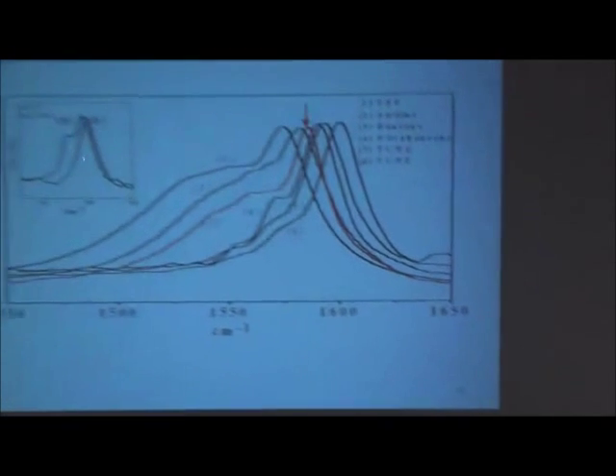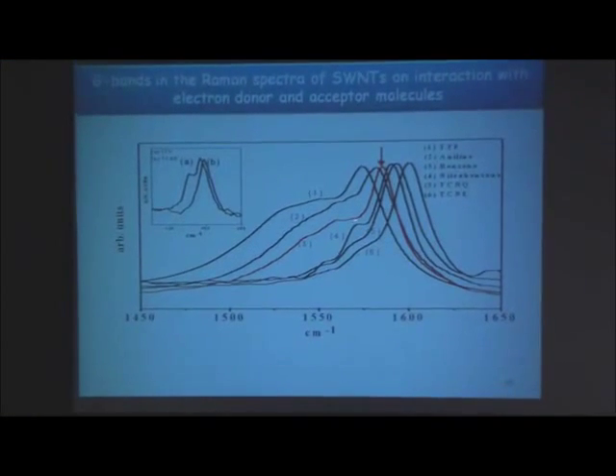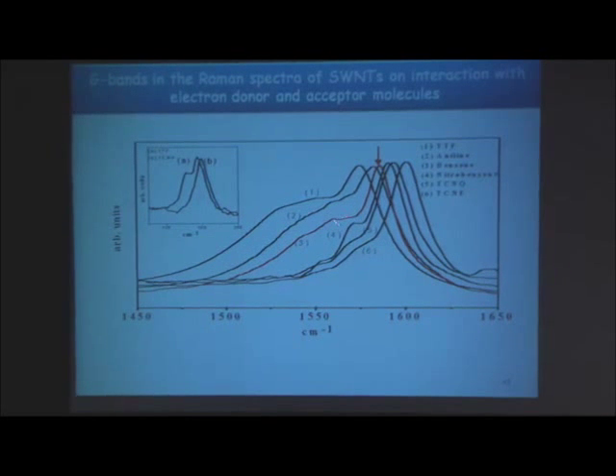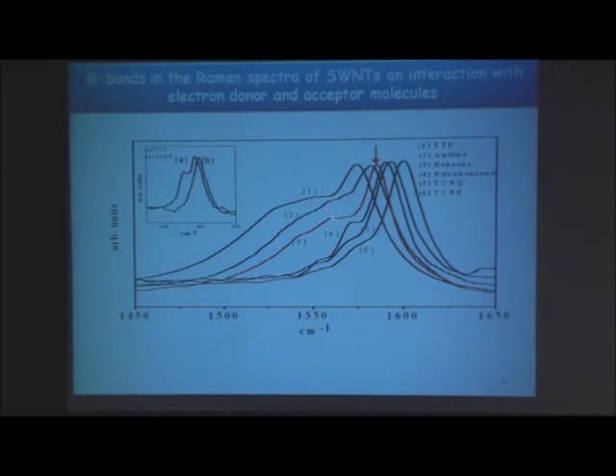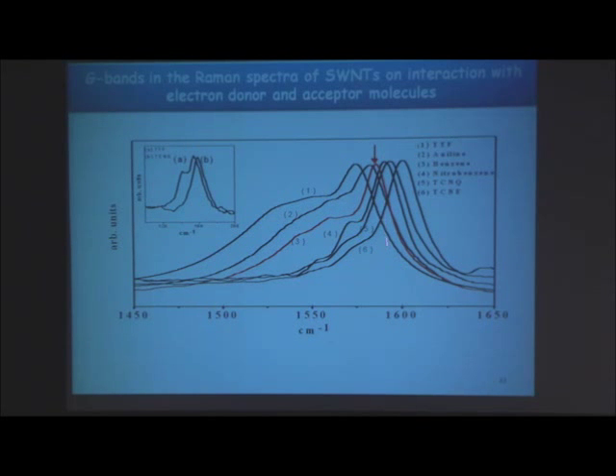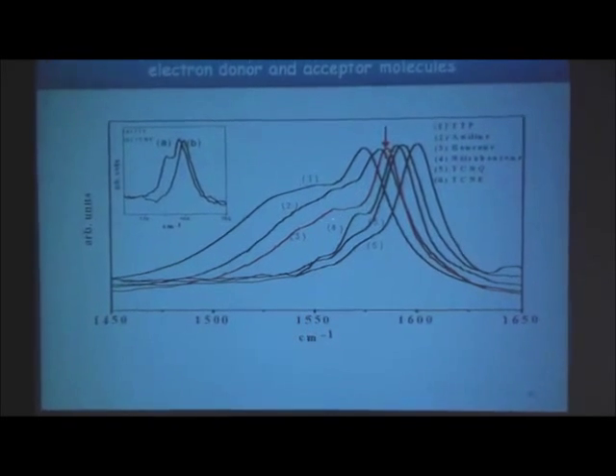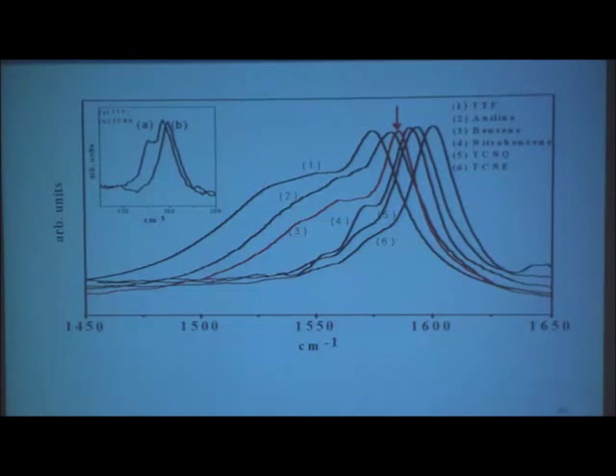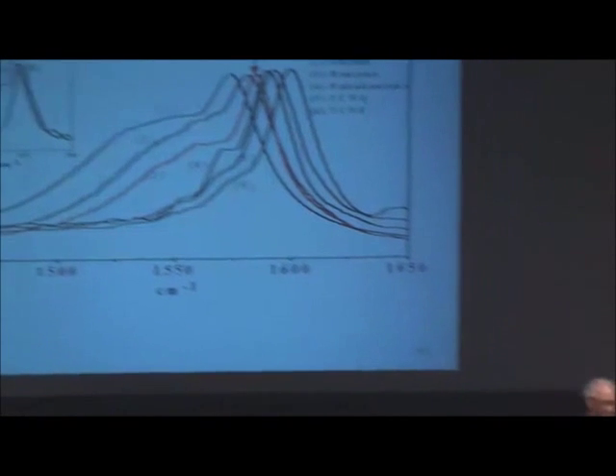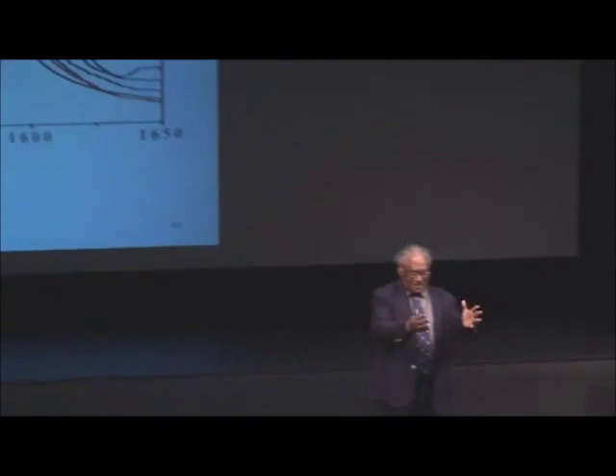This is the Raman spectrum. You see, the red spectrum is the spectrum of nanotubes as you make them. As you make it, it is a mixture of semiconducting and metallic nanotubes. That shoulder there, 1540, is characteristic of metallic nanotube. The big red band is mainly due to semiconductor nanotube. How do you know that? Well, there is a very nice paper by Ajay Sood and myself in Physical Review Letters last year to show which is which in the nanotube Raman. For those interested, you can see that. And that is the metallic.